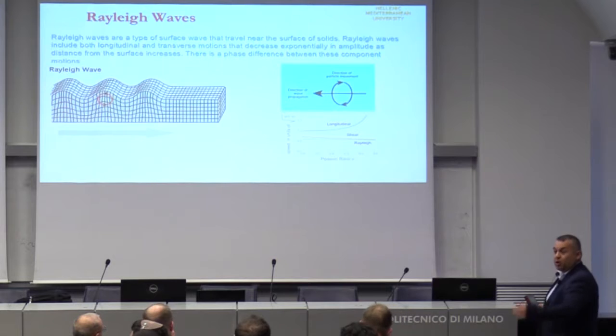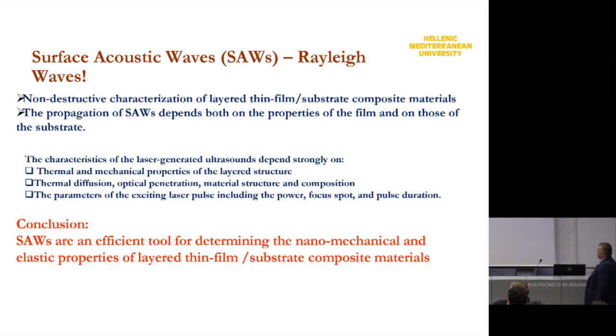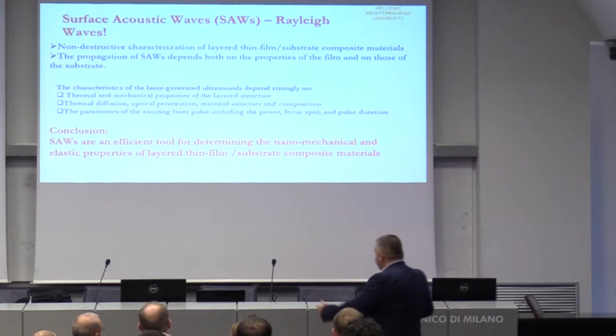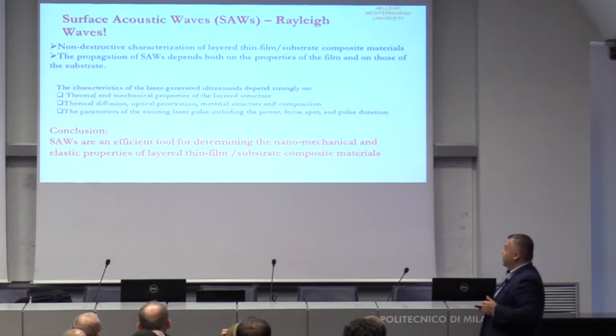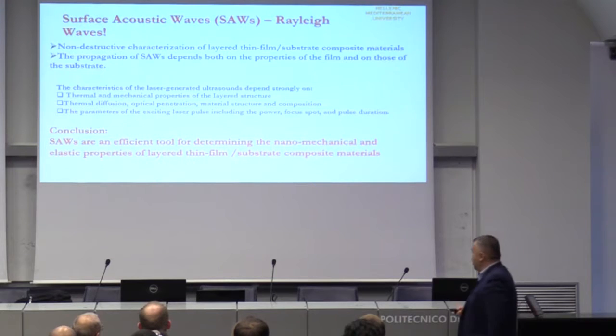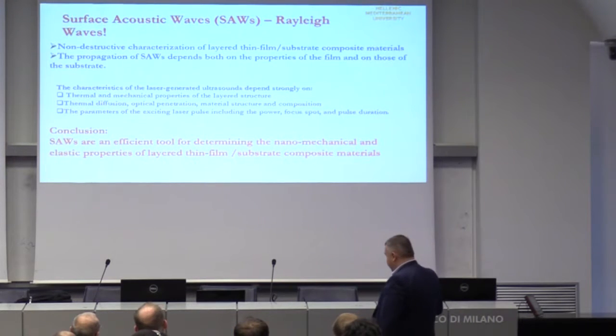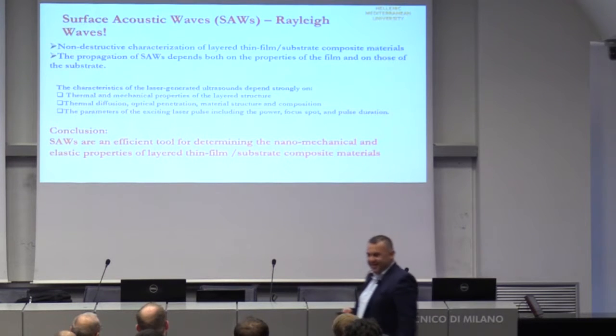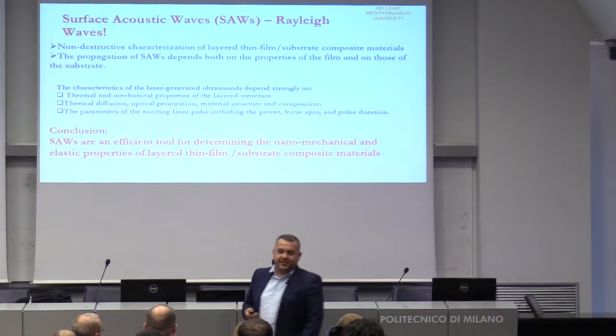How can we produce, control and observe this kind of waves on a surface? First of all, we have non-destructive characterization of layered thin films. The propagation of surface waves depends both on properties of the film and of the substrate, as we have seen. And there are a lot of applications because these laser-generated surface waves depend a lot on thermomechanical properties of layered materials, thermal diffusion, optical penetration, material structure and composition, but also on the parameters of the exciting pulse, including of course power, focus spot, pulse duration, chirp. So it's worthwhile to study these effects, and laser is a good tool.